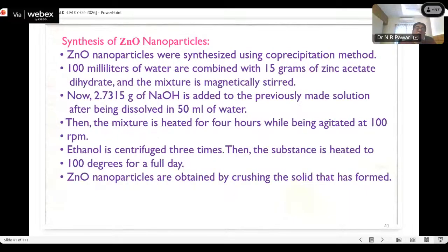Then this nanoparticle is also used for the synthesis of the hybrid nanofluid. These ZnO nanoparticles were synthesized using the co-precipitation method, because we have discussed a number of times that many nanoparticles are synthesized by the Sol-Gel technique. So we have to synthesize this type of nanoparticle by using some other technique.